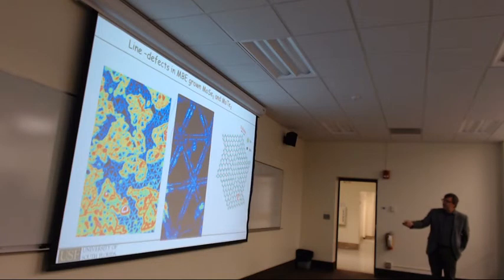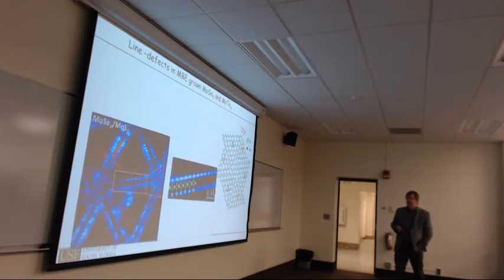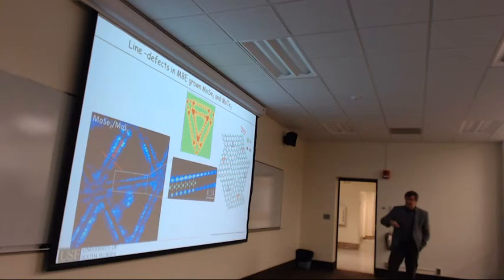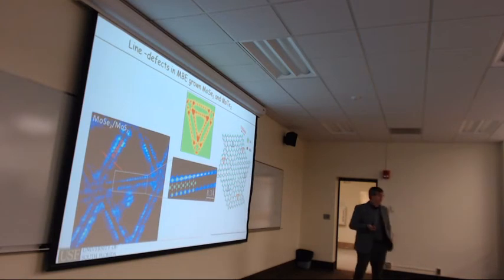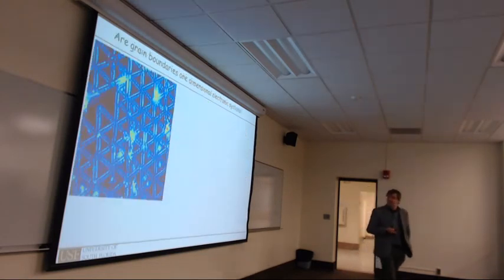You have one twin like that, the opposite twin, and again, and going back and forth. You get these twins, and in between you get all these twin grain boundaries. And what we image in STM are actually the selenium atoms that are neighboring the actual grain boundaries, which is shown here in more detail. So these are just the atomic corrugation of the selenium atoms. And that agrees well with simulated STM images of this structure.